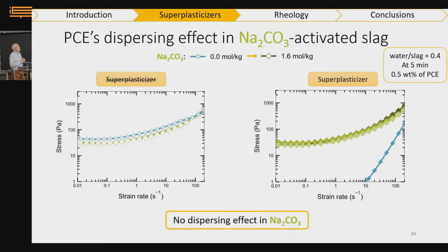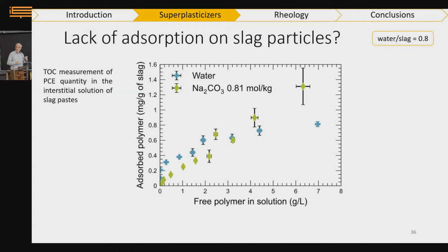Now a more complex case, sodium carbonate. Sodium carbonate, again, without superplasticizer, does not change the yield stress of the suspension. But when I put the superplasticizer, again, the yield stress disappears. But when I put the sodium carbonate, boom, it comes back immediately. So we don't have this gradual effect that we had with sodium hydroxide. So something else is at play here. And this is what I had ruled out for sodium hydroxide: the poor adsorption comes back into the picture here. You can see that with sodium carbonate, the amount of polymer adsorbed is much lower than without sodium carbonate.